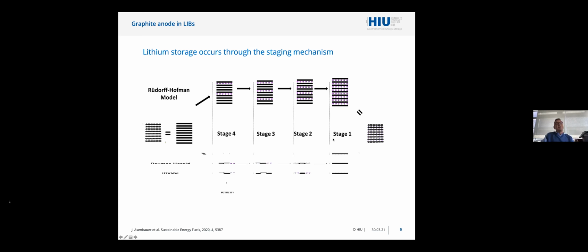What does this mean? This staging mechanism is very well seen when we do the lithiation and delithiation of graphite, and we record the potential or the voltage, depending on whether we have a 3-electrode or 2-electrode cell. What we see are these typical steps, which occur when a certain staging